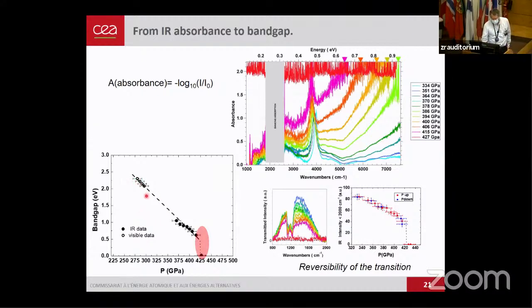And though the band gap is decreasing, this was the visible measurement we did some years ago. And at some stage, you have a decrease, and so the band gap is going to be very small. There was some discussion on our data saying you cannot say that the band gap has closed because you cannot go below 0.1 eV.